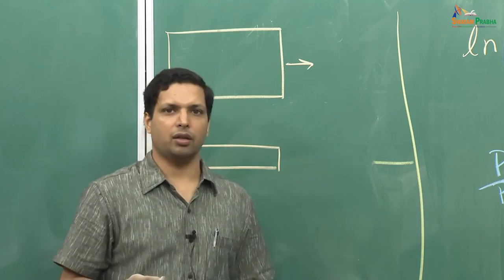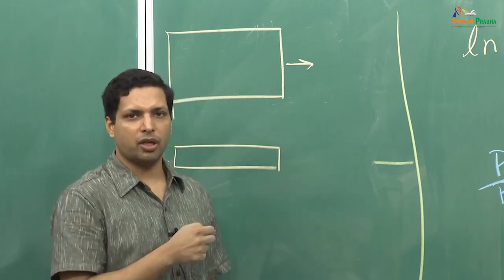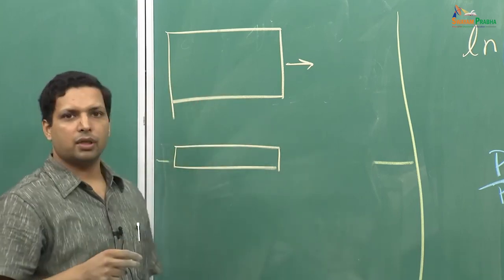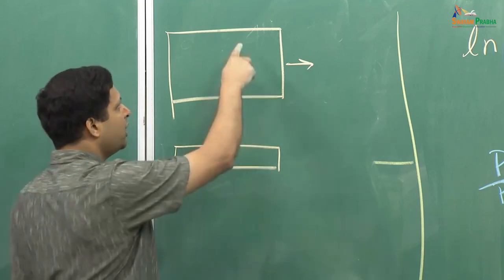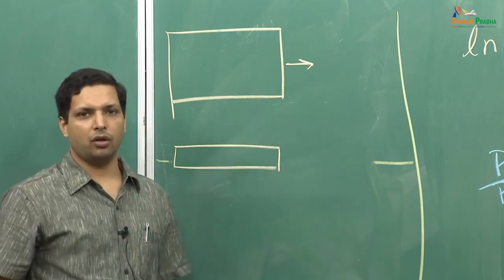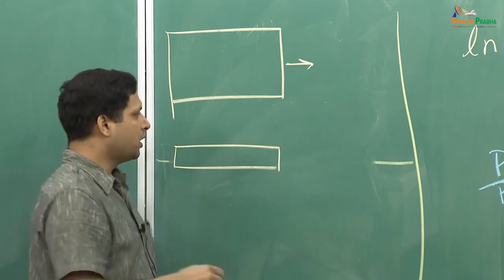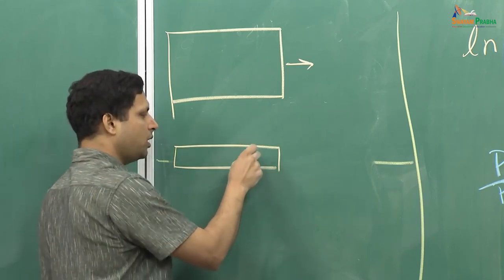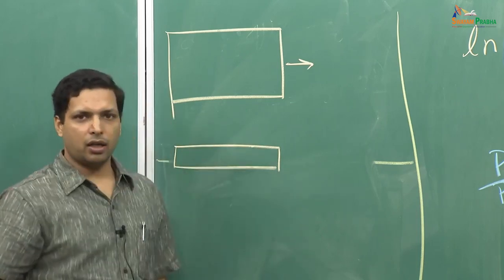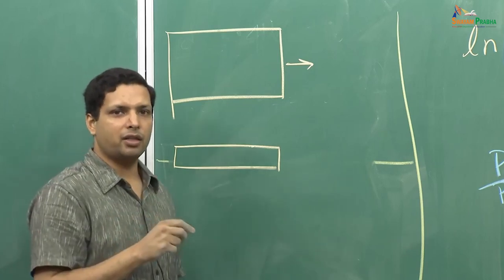Here the total pressure change delta P is much smaller. What does that imply? When the pressure drop is very large, it means the density would also change accordingly. Here you will get higher density at the top and much lower density in the lower region, but for the thinner compact the difference would be much smaller. And that has an implication in the shrinkage during sintering.